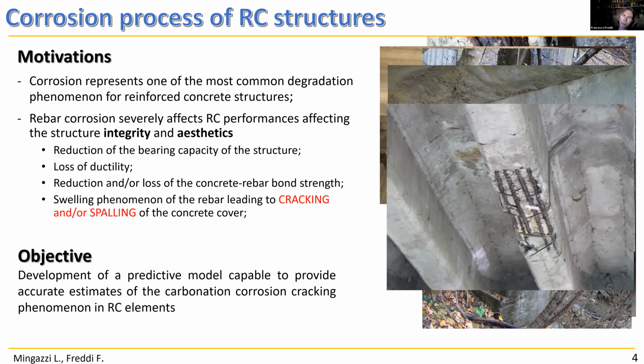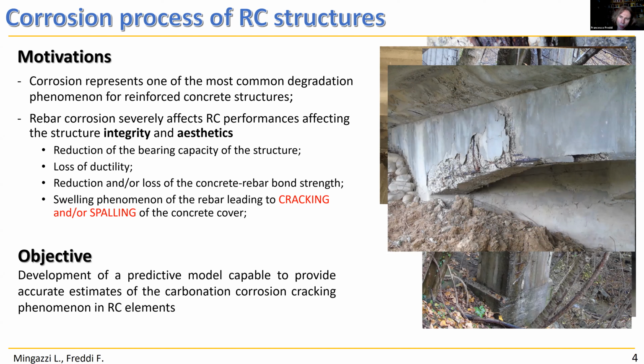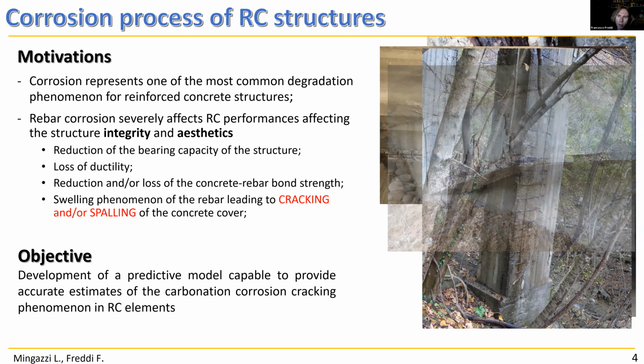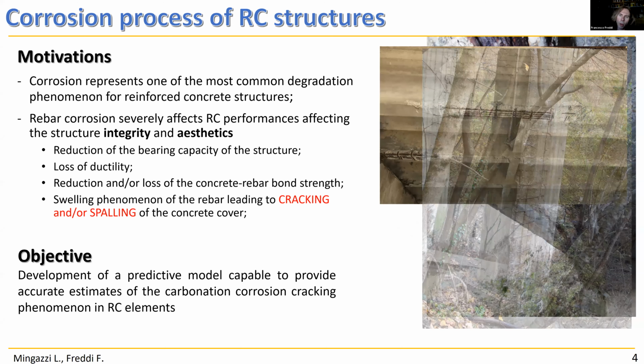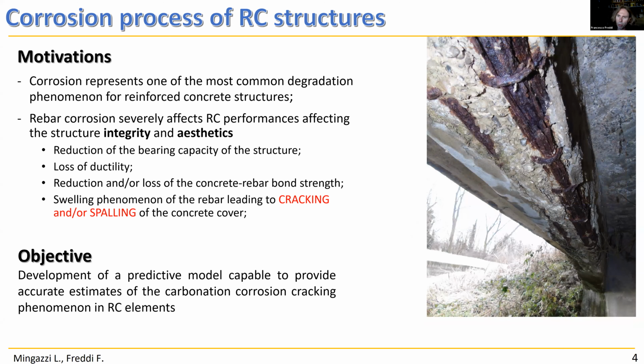And another important phenomenon is the swelling of the rebar that leads to concrete cracking and spalling of the concrete cover, which is extremely important to protect the bars from environmental conditions. So the objective is to present a predictive model that can describe, at least at the microscopic level, the cracking caused by corrosion of the bar. The images you see on the right of the screen are just some examples of rebar corrosion taken from some bridges.